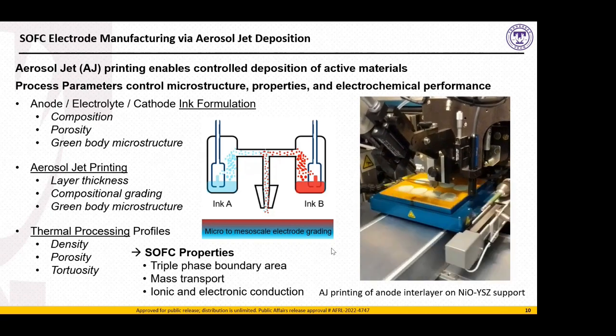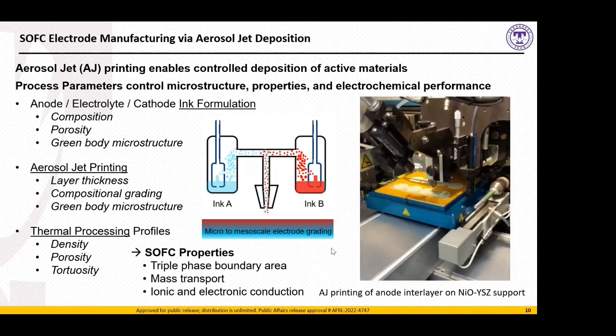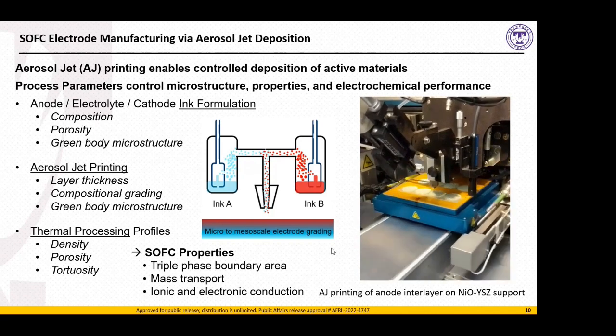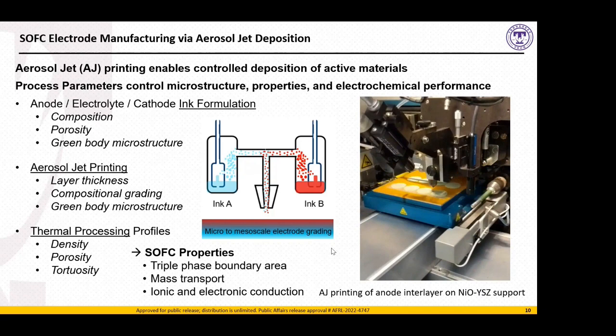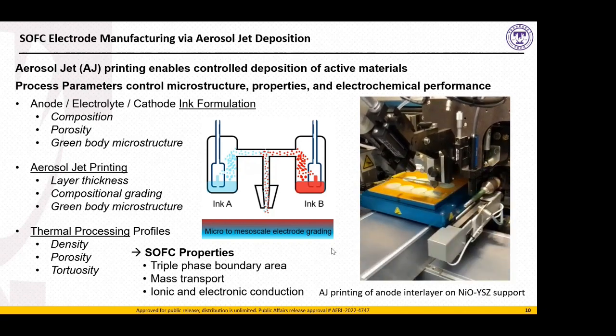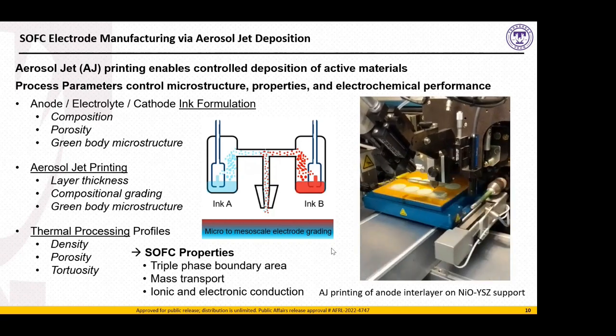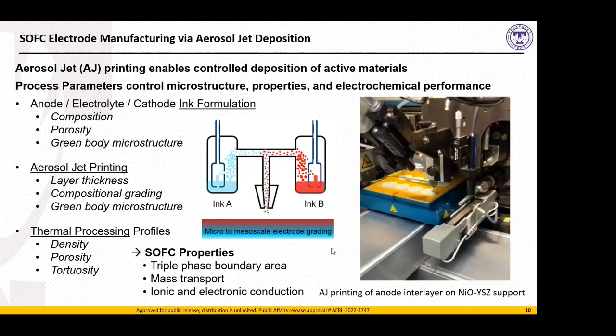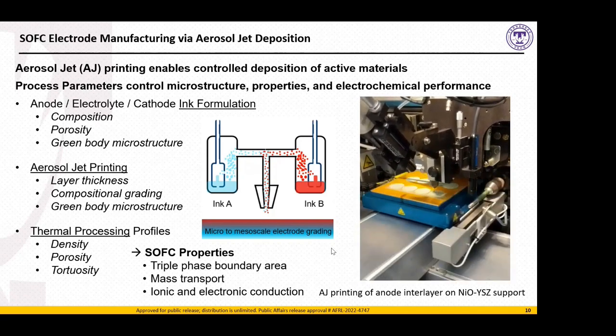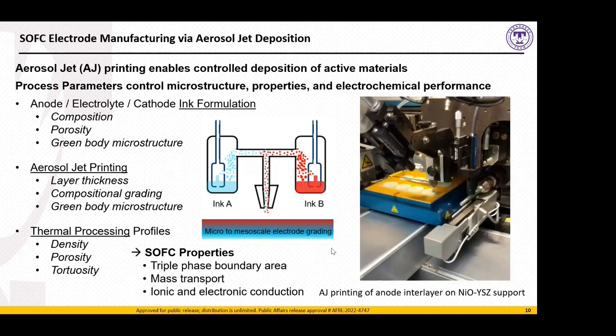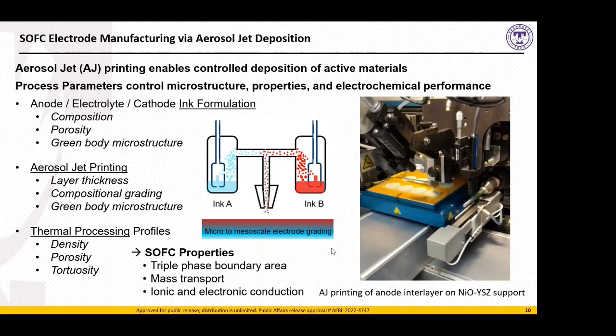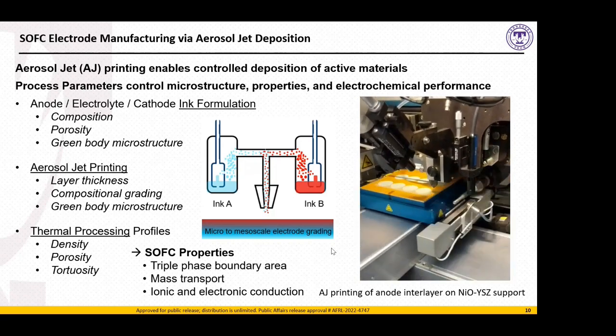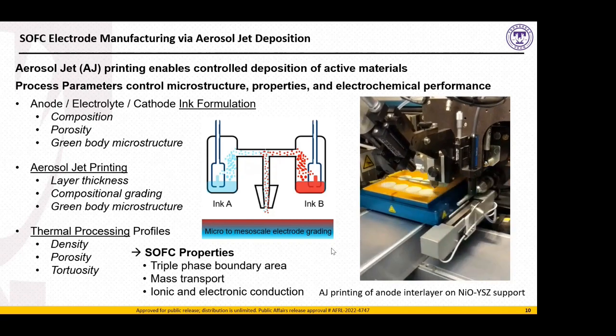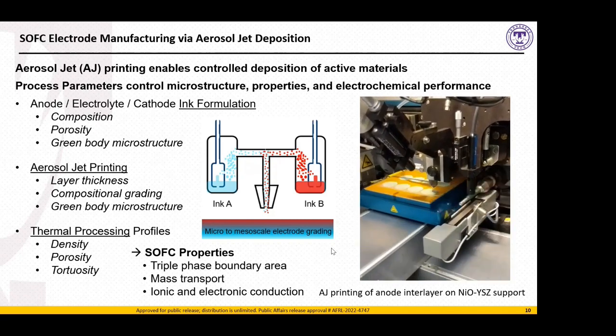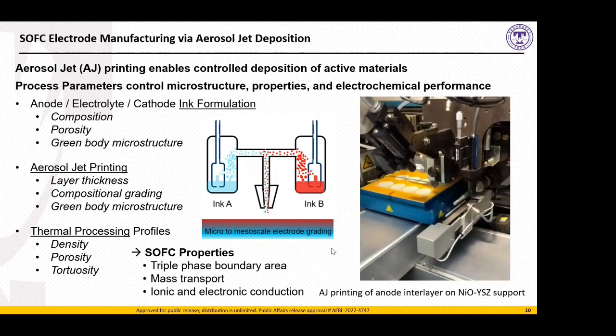And on the manufacturing end, again, thermal processing profiles will affect the density and the porosity and the tortuosity of the final cell. The tortuosity is the effective path that is added as a result of the twisting, the turning that any kind of charge carrier or molecule must proceed through, in contrast to the geometric dimensions. On the right-hand side there, you see a video of the aerosol jet deposition happening in printing coupon cells or button cells.